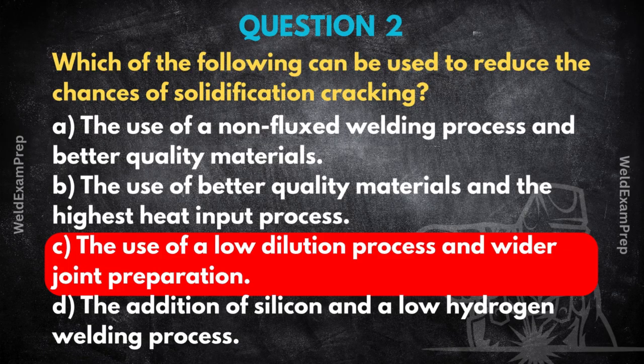Think of it like this. As the metal freezes, impurities like sulfur or phosphorus get pushed into the last bits of liquid between the solidifying grains. These liquid films at the grain boundaries are weak points. Then, as the weld shrinks during cooling, these weak spots can just tear open under the stress. Like pulling apart something that's not quite set yet.